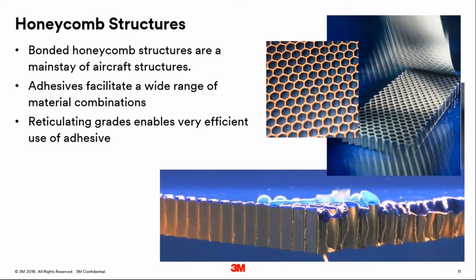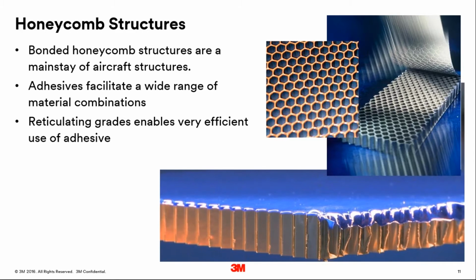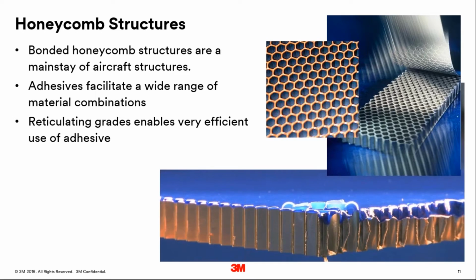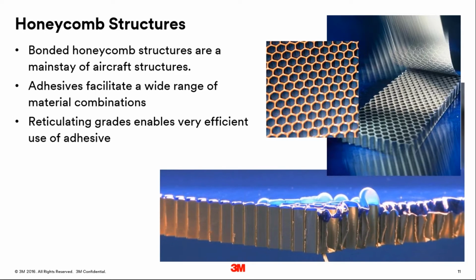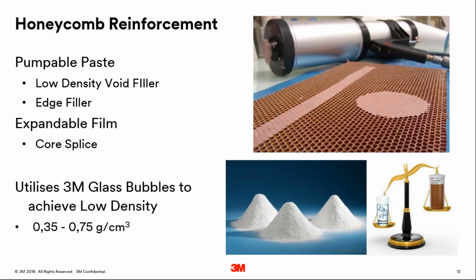However, honeycombs have their own restrictions when we go to join them. We might need to make a T-joint or a corner or indeed embed a fixing into the honeycomb. Therefore, we've developed grades of low density void filler, which can be used to locally reinforce the honeycomb so that we can make a joint.